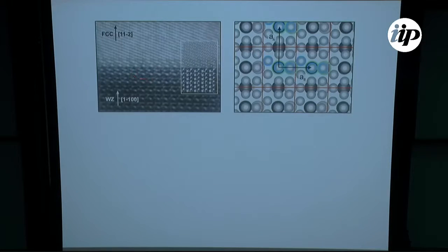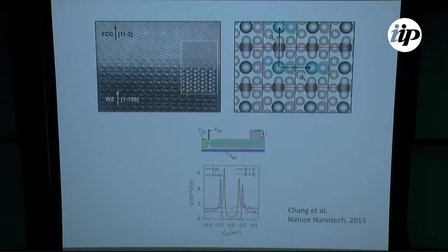Here is a close-up on the interface of this kind of nanowire, and if we try to simulate how they match up in this 3:2 ratio, and you look in normal on the interface, there's a very small interfacial domain, and it persists throughout the nanowire. So it has a low level of disorder along the interfaces. And this gives a hard gap. At least it looks like it's found one of the main sources for a soft gap. And we compared with the soft gap here from the conventional way we did it before.